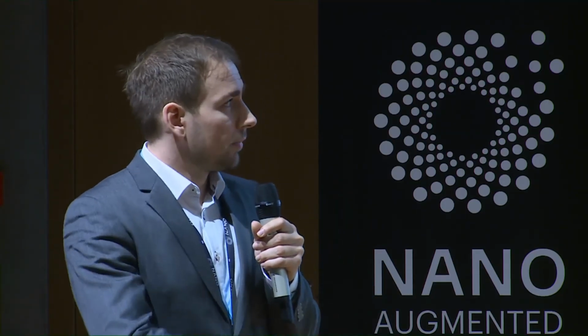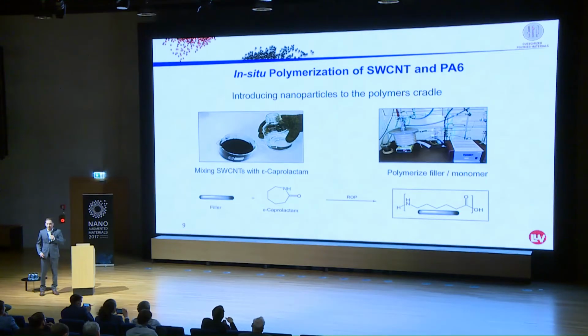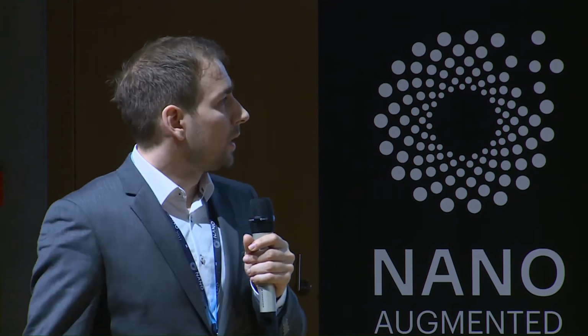Afterwards, you polymerize it in this lab scale reactor here, up to 5 liters. The chemistry behind it is quite simple. It's a ring opening polymerization, so it's nice to handle. And we got this composite material here in one step, so no further compounding is needed. Let's have a look at the product of this in-situ made TUBALL PA6 compound.